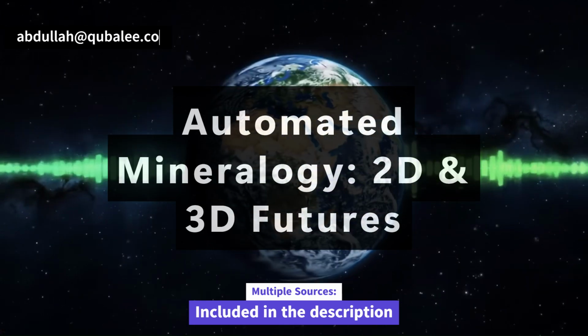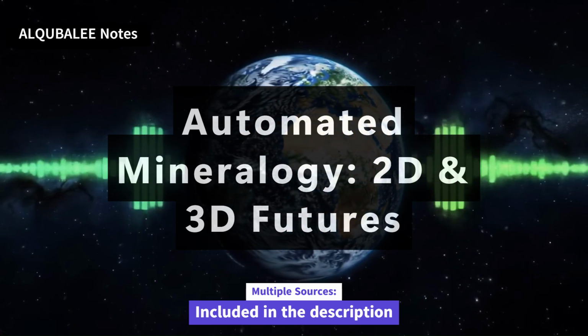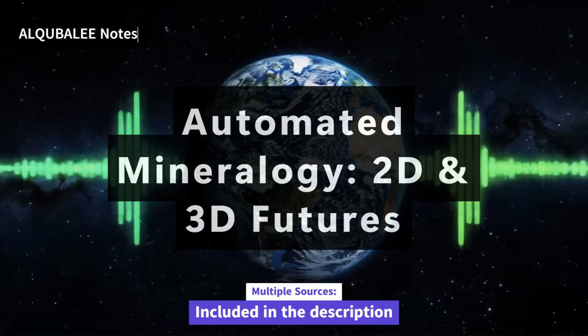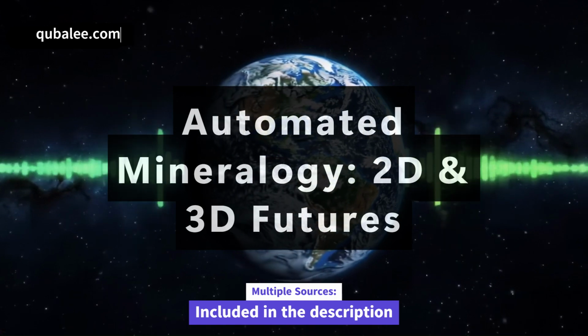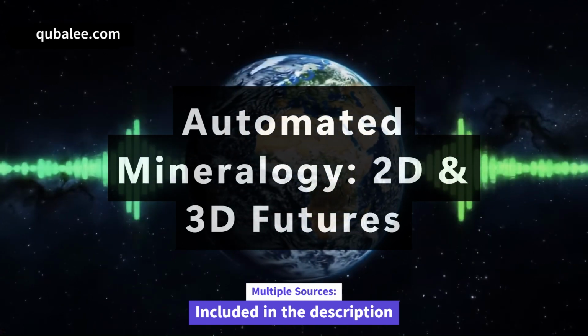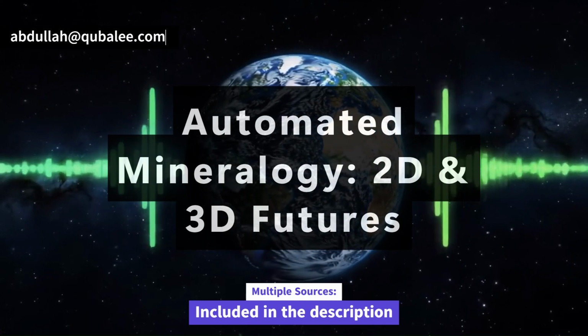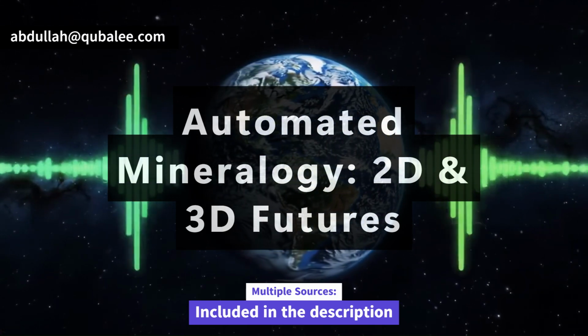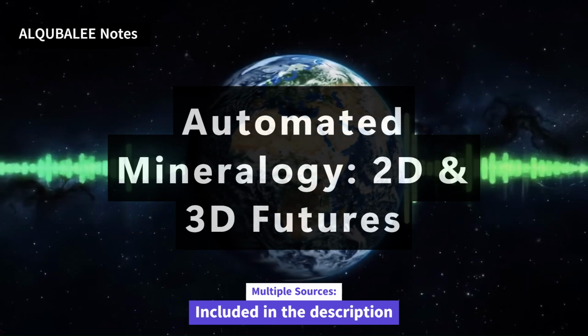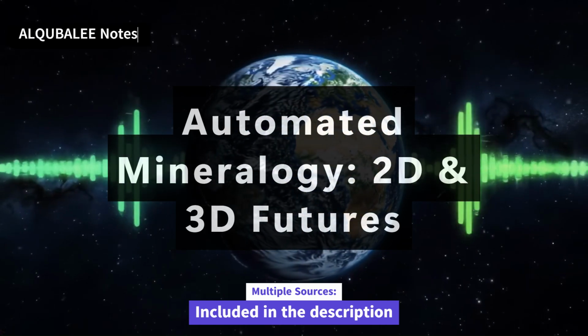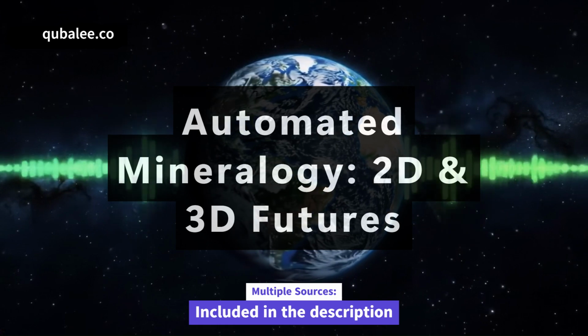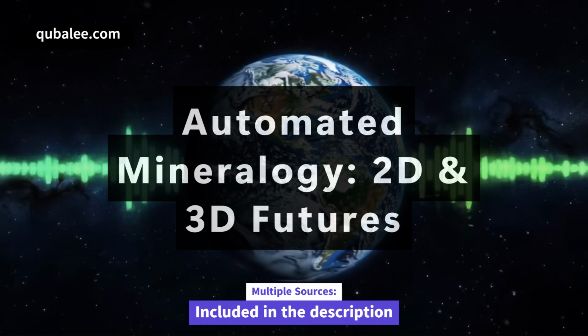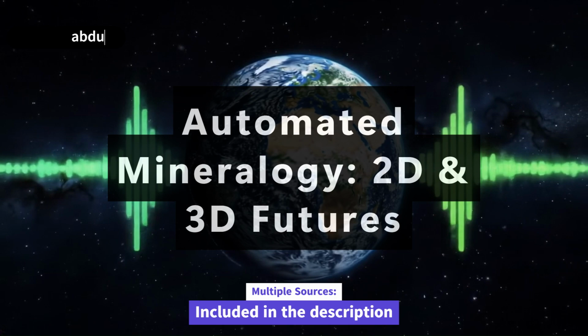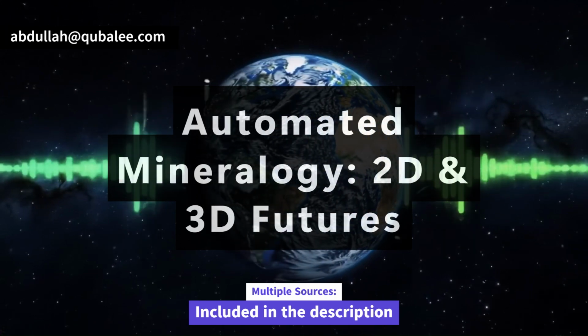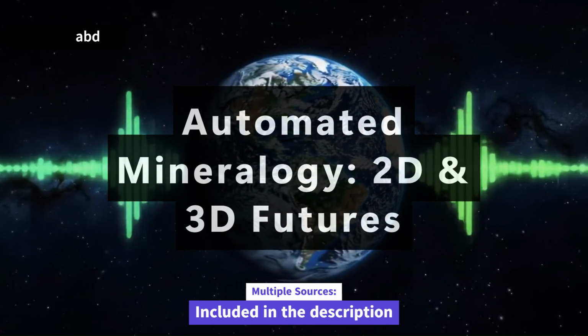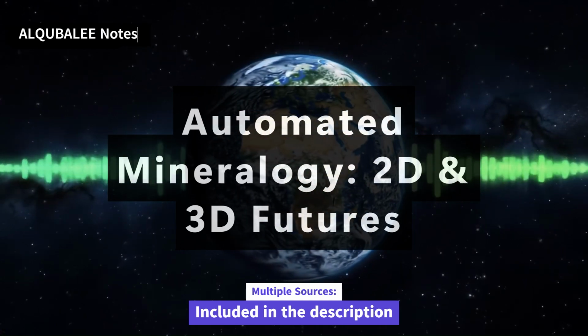It's more robust. Okay, so we've got this amazing pixel-by-pixel analysis happening, but one of the huge advantages the sources kept highlighting was scale, the ability to analyze really big areas, like a whole geological thin section. How does it manage that large scale, but still keep the detail? That's a key part of the automation. The system is programmed to automatically acquire data from many, many small, high-resolution fields of view across the sample. Like taking lots of small pictures. Exactly. And then it stitches them together digitally, seamlessly, into one large map of the entire area you defined.